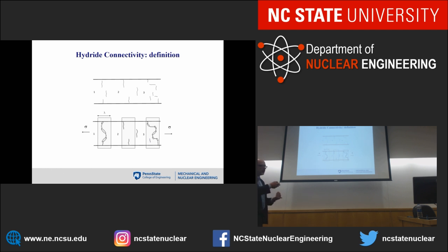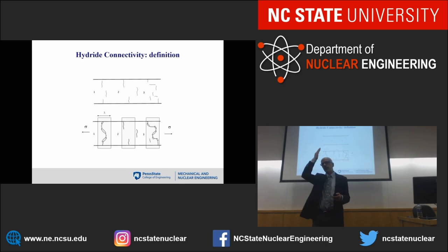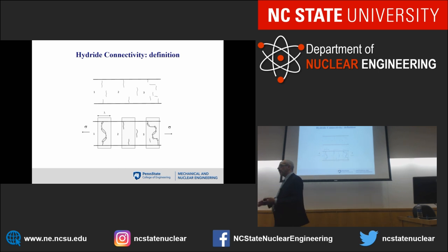What is the fraction of the thickness that needs to be covered by this ductile failure? And that's what's going to control failure in the alloy, in the hydride. So it's really dependent on how connected these hydrides are. And what turns out is that if I cycle the material several times, dissolve, reprecipitate, dissolve, reprecipitate, they get closer and closer packed.